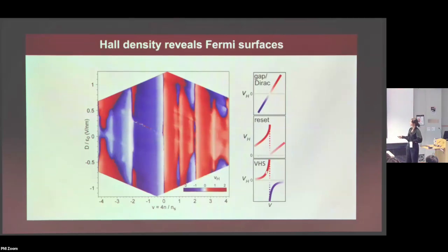And the last type is this Van Hove singularity, where your Hall density all of a sudden goes to infinity, and then again all of a sudden changes sign. So this Van Hove singularity shows you that there's some sort of saddle point in your Fermi surface. These Van Hove singularity features are happening at very high displacement fields in certain regions. Okay, so this is the Hall density, which can tell us more about the electronic structure.